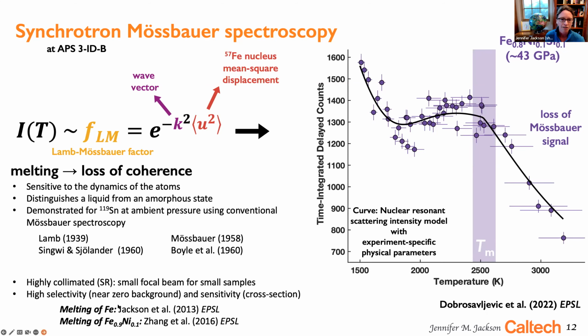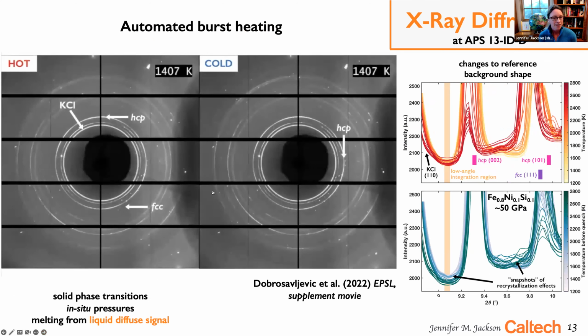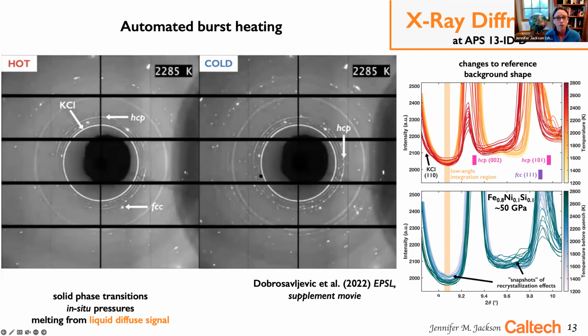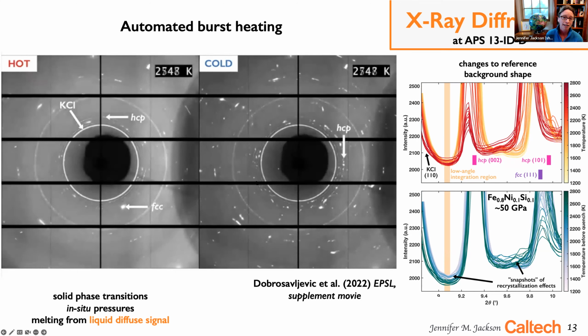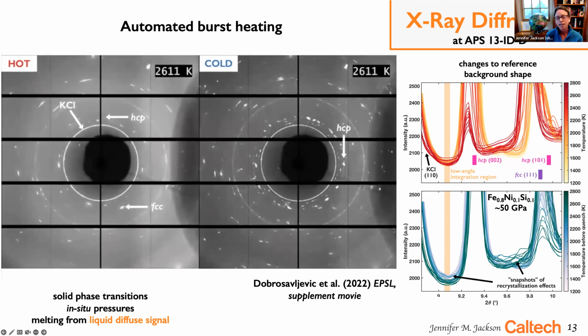Okay, now we turn to the X-ray diffraction experiments. We conduct these at GSECARS using an automated burst heating method that they have developed, collecting first a hot pattern followed by a cold pattern. Here is a temperature sequence that we put together. In the scattering process of diffraction, of course, everything with an appropriate scattering cross-section in the focal volume contributes to the measured signal. Typical analysis of trying to detect a signal from a melt from such a suite of patterns involves detecting an often subtle signal that must rise above all of these other scattering contributions, essentially trying to detect a change in the shape of the background of the signal.